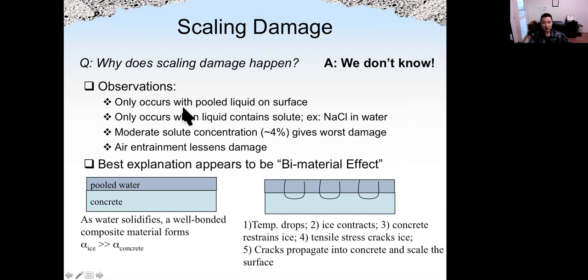It only occurs when we have liquid on the surface of concrete, and only when the liquid contains salt, a solute, for example sodium chloride or other de-icing salt. And certain concentrations will cause different types of damage. To reduce this type of damage, we could introduce air entraining agent in concrete to reduce the possible scaling damage. And the reason for the scaling damage can be explained by the so-called bimaterial effect.